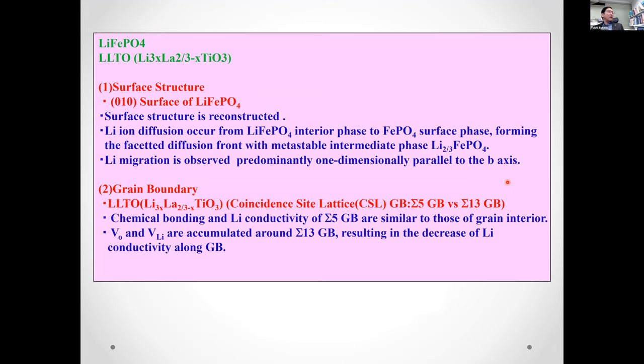So I want to summarize my talk. Today, I showed two examples. One is surface structure characterization of the olivine iron phosphate structures, and we found that the surface structure is reconstructed. And lithium ion diffusion occurs from inside to the surface, forming a faceted diffusion front with a metastable intermediate phase. This is Li2/3FePO4, and the lithium migration is observed predominantly one-dimensionally, parallel to the b axis.